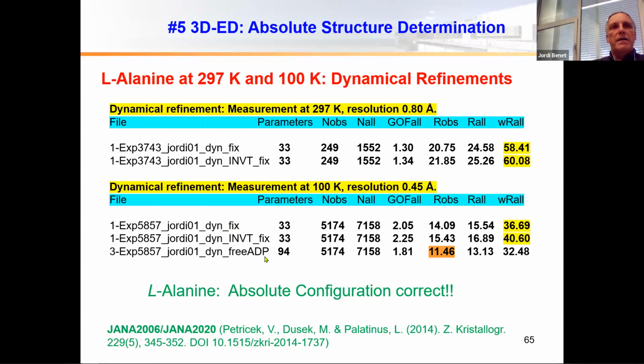Of course, if you finalize the data set to a proper refinement, for example, this crystal here was refined dynamically, and we went down to an R value of 11%, which is quite nice. But the important point is that the big difference in the R value was showing us always which one of them was the correct absolute configuration. So in this case, we don't need a flack parameter. In this case, the differences are coming from the so-called dynamical effects, which are much stronger than the anomalous dispersion effects on X-rays.